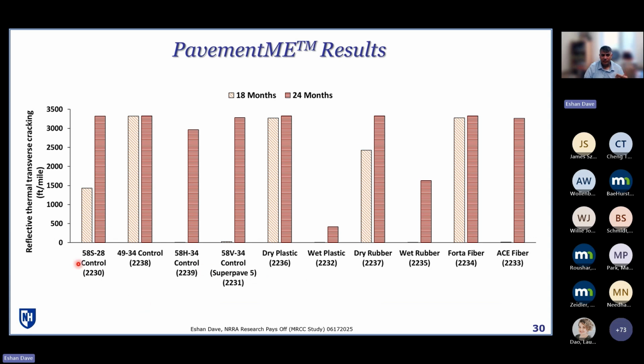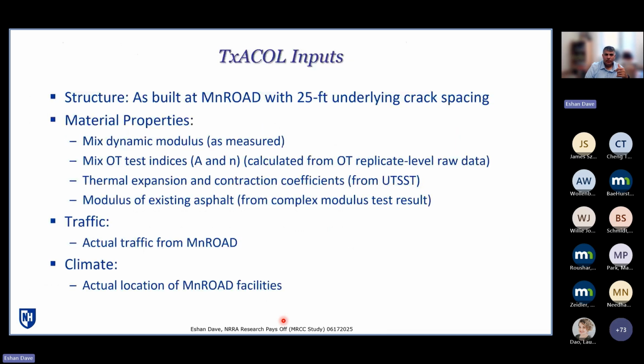When you look at traditional asphalt mixtures, as in these three, especially 58H minus 34 and 58S minus 28, then it makes sense: a polymer modified mixture usually shows no cracking when you have some cracking in control. When control is almost fully cracked, there's still less than fully cracked in this case. But when you look at rubbers, plastics, or fibers, I don't think you can really trust the pavement ME results. So that's where we also looked at another tool called TxACOL, which is developed by TTI. It uses the overlay test as an input, and it simulates your fracture mechanics based crack growth.